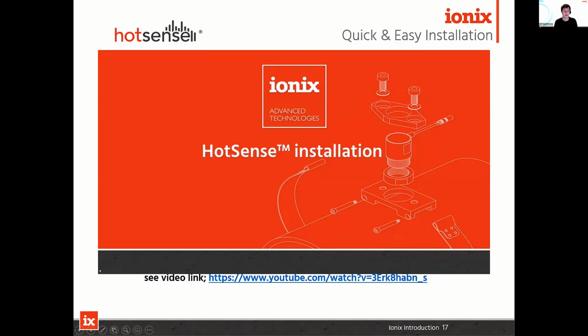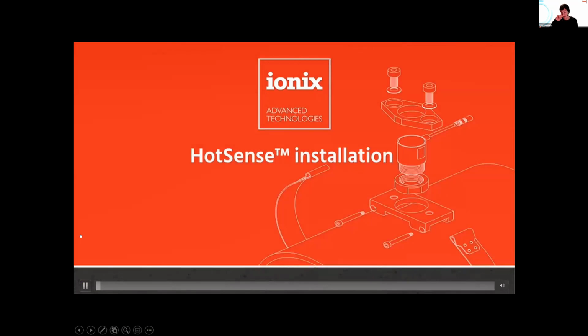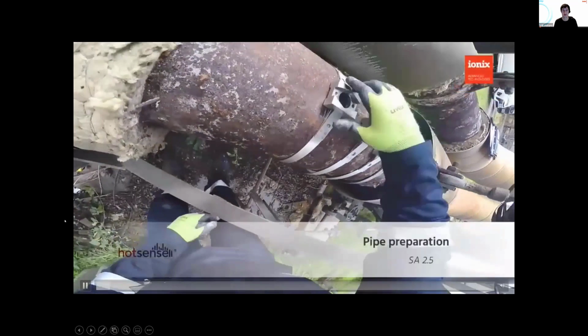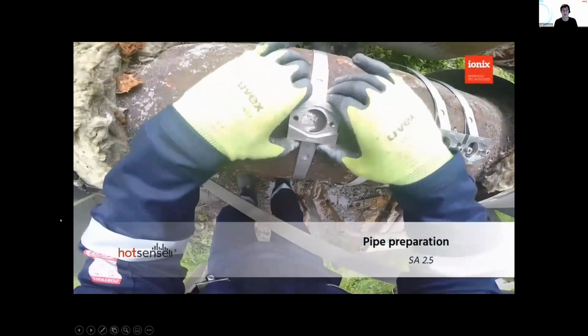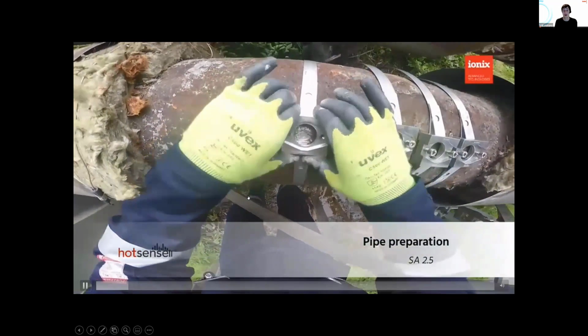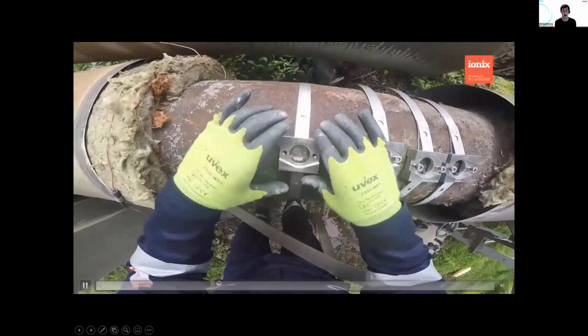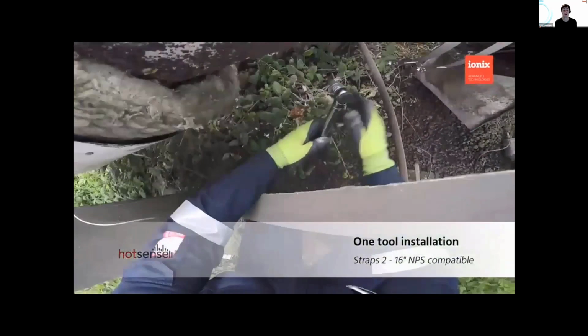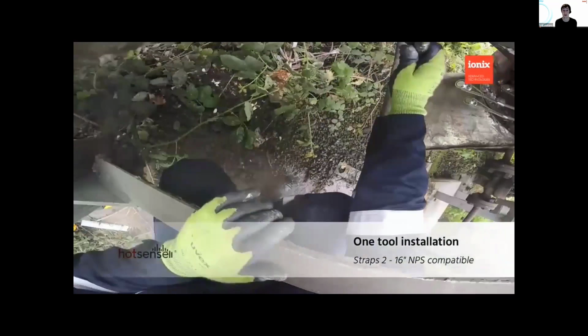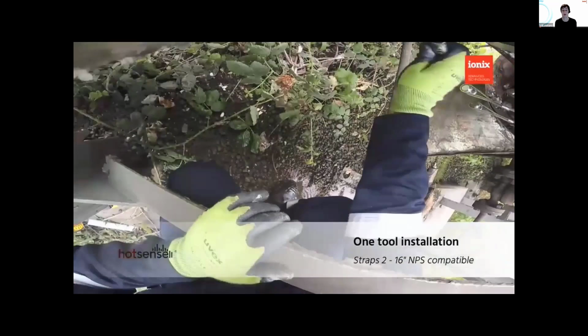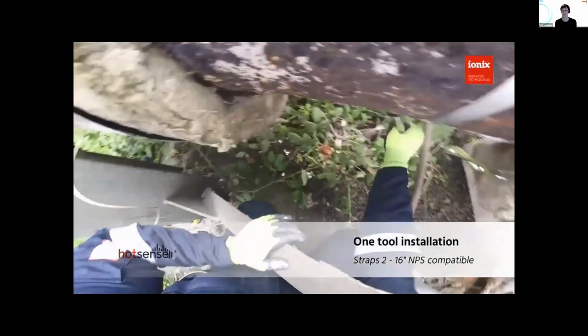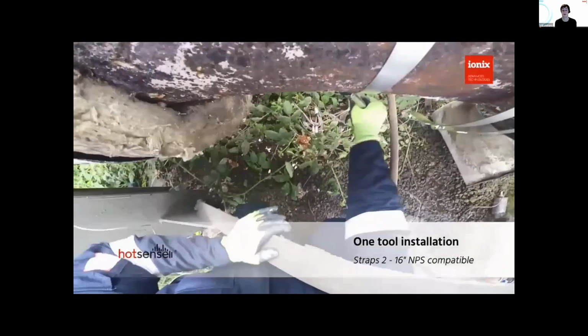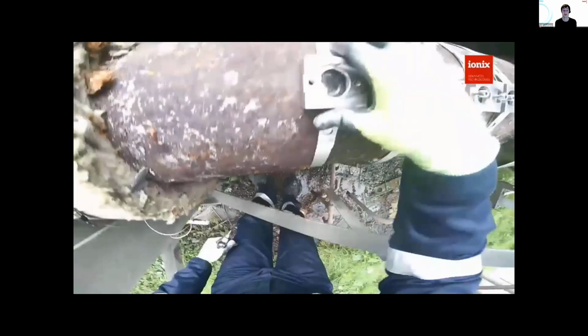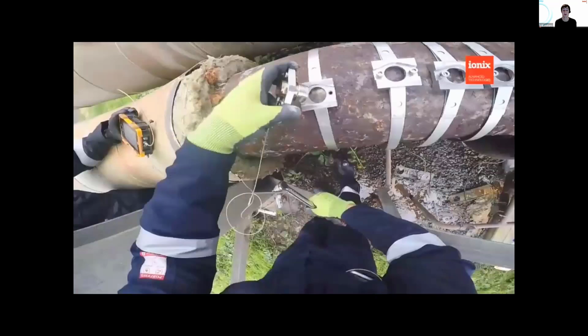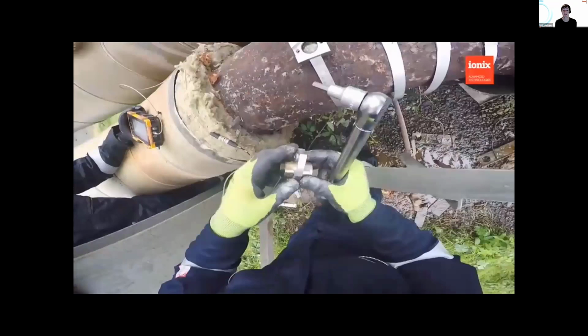The installation of the probe is extremely simple. I'll show a video here of it being installed on a pipe. I think this is at about 230 degrees C. You have to remove surface coatings and any roughness, down to a near white metal finish. It can be done just using a simple hand file. You don't want to flatten the pipe. We're trying to minimize the removal of material here, but it's really just getting rid of coatings and rust. Tighten it using a wrench on the strap,